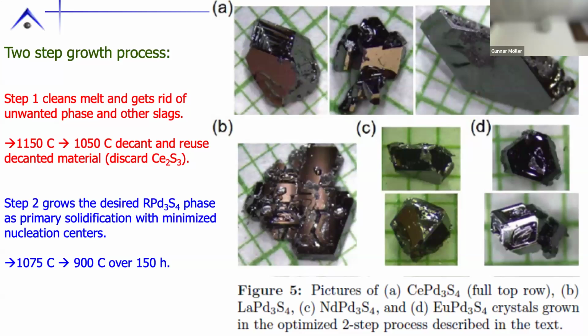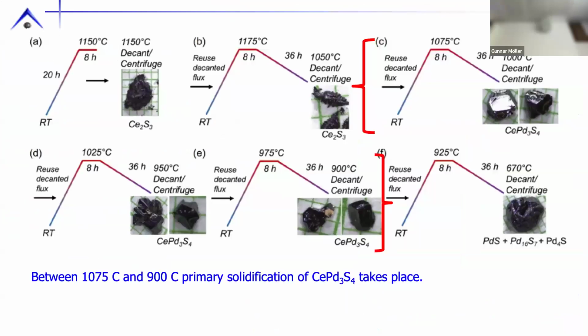oxysulfides. Yes? Do you switch between the temperatures very quickly, or do you let it cool, come back later, go again? So we heat up, go to 1175, dwell there for 8 hours, 36 hours down, decant. Now, in reality, when we've been doing it even quicker, I get in early in the morning. So I get in at about 6:30 a.m., not p.m. So I decant, have my coffee, come back, open it up, see what there is, reseal, put it back in the oven. It's in the oven by 8.